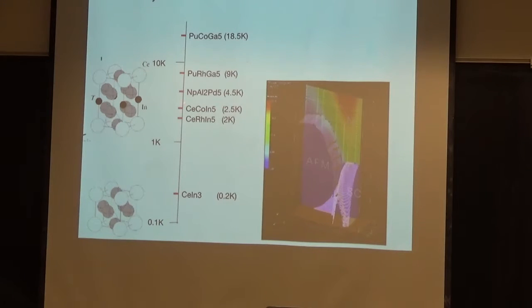And then, this is all in 2001, the idea was, why not replace the cerium by a 5f material? And when you do that, you have to mess around, so you'll have to adjust the size of the indium atom. Let's go to gallium. And experimentalists at Los Alamos then discovered plutonium cobalt gallium 5, which is an 18.5 Kelvin superconductor. And shortly thereafter, this 9 Kelvin plutonium rhodium gallium 5 superconductor. Along the way, more recently, by accident, neptunium palladium aluminium 5 was discovered.